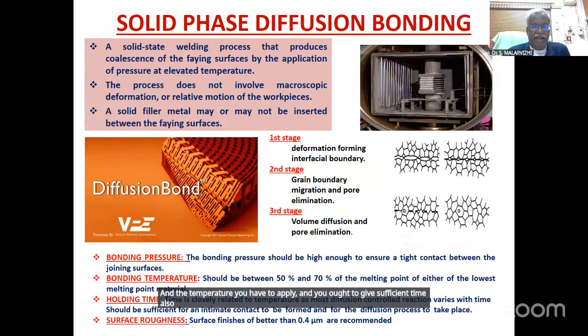So bonding pressure, the pressure should be high enough to ensure high contact between the two joining surfaces, but it should not exceed the yield strength, because if the bonding pressure exceeds the yield strength of the material, then the material gets deformed. So the shape and dimensions will get affected.